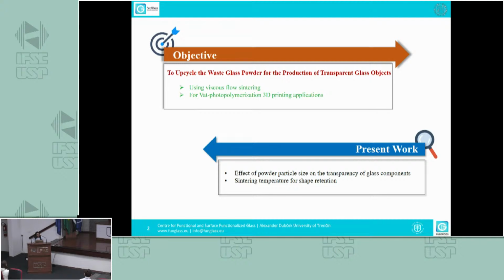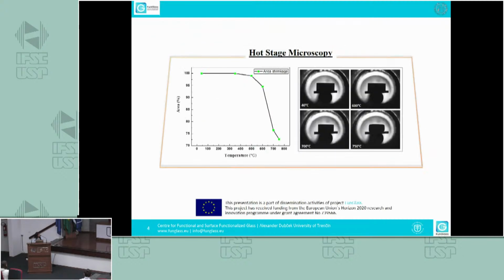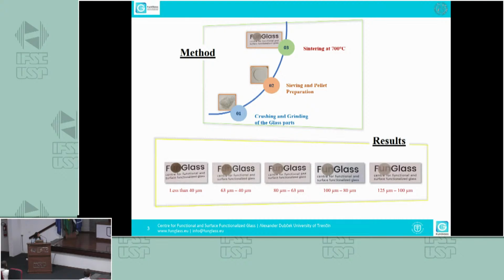Because if I am producing a 3D printed part, some additive manufacturing methods require post-processing, like debinding and sintering. And if I have produced a 3D printed part and I want to go to sintering, I want that 3D structure to be retained, not destroyed. So it is important to know what the sintering temperature should be, so that the shape of the green part or the final product is retained. This is the method that I have used, which I will be explaining during my poster.